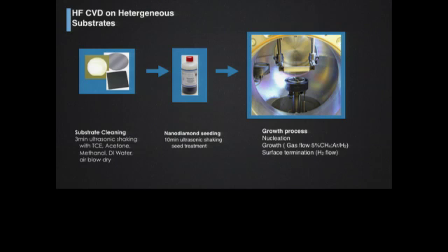We also have to control the concentration of the gases so that we can grow diamond versus graphitic material. There's a competition between diamond and a graphitic material that can grow, and by adding certain gases like argon, you can force the reaction to go in the favor of diamond versus graphitic, and I'll show you how we can prove that that's the case.